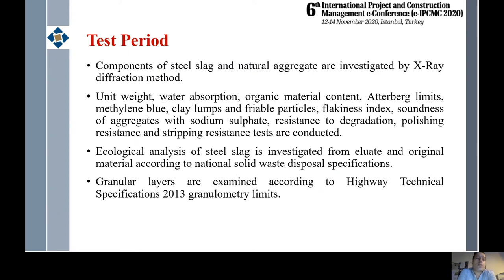After the beginning of the project, the test period has started. In the test period, first of all, the components of steel slag and natural aggregate are investigated by X-ray diffraction method. Unit weight, water absorption, organic material content, Atterberg limits, methylene blue, clay lumps and friable particles, flakiness index, soundness of aggregates with sodium sulfate, resistance to degradation, polishing resistance, and stripping resistance tests are conducted.